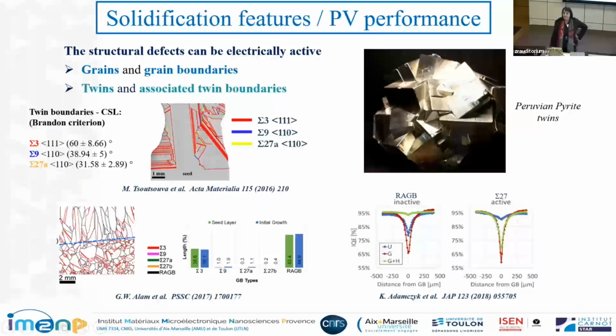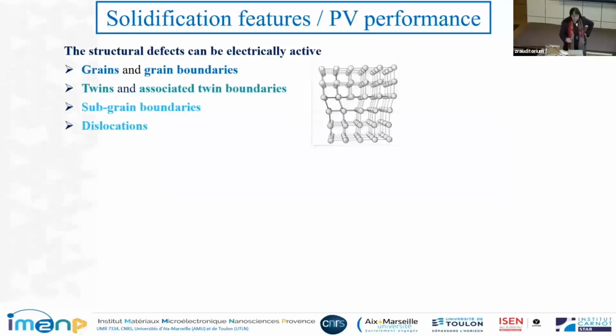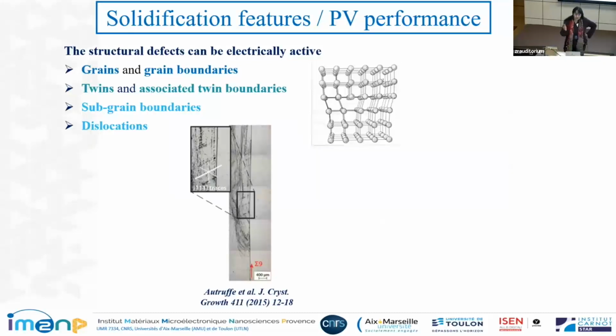And the impact is here. Depending on the type of grain boundary or twin boundary, you have different electrical properties at the level of these boundaries. Here is a random angle grain boundary, and it can be cured during the fabrication of the solar cell, which is not the case for this sigma 27 twin boundary. When you go down in scale, you have subgrain boundaries and dislocations. And also there are very small defects, atomic scale defects. They will have an impact as well on the electrical properties.